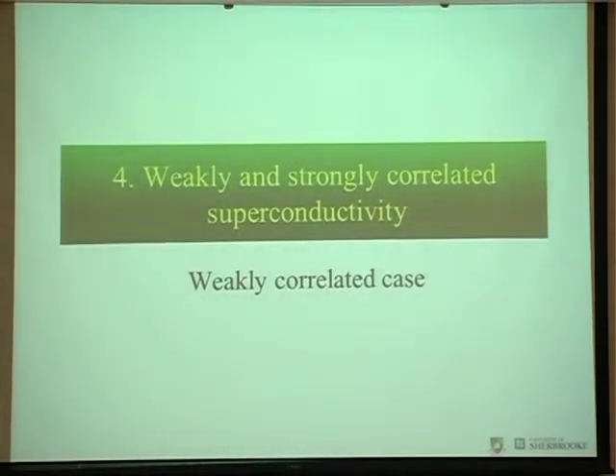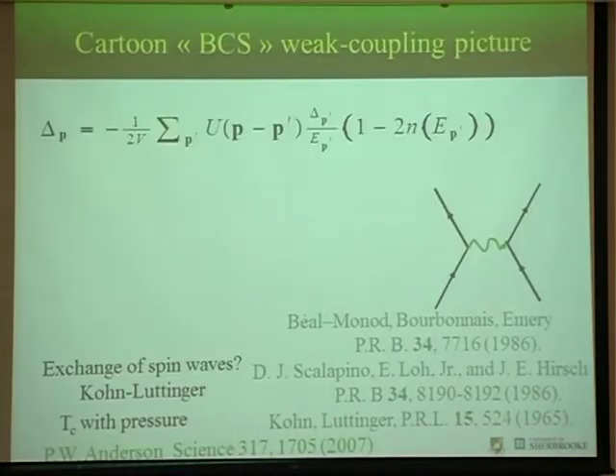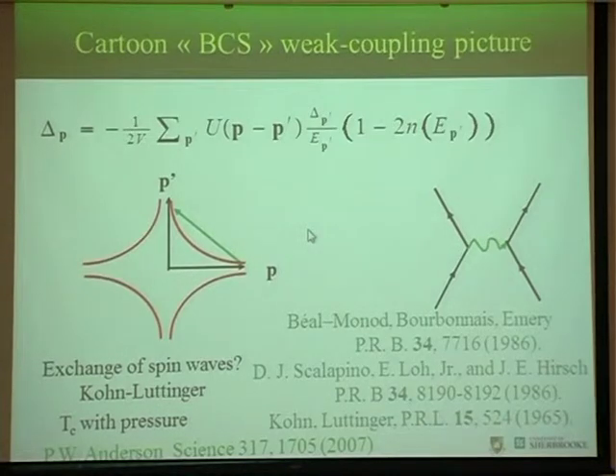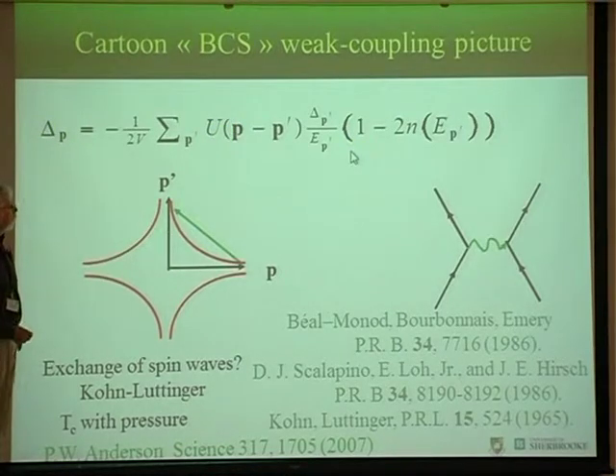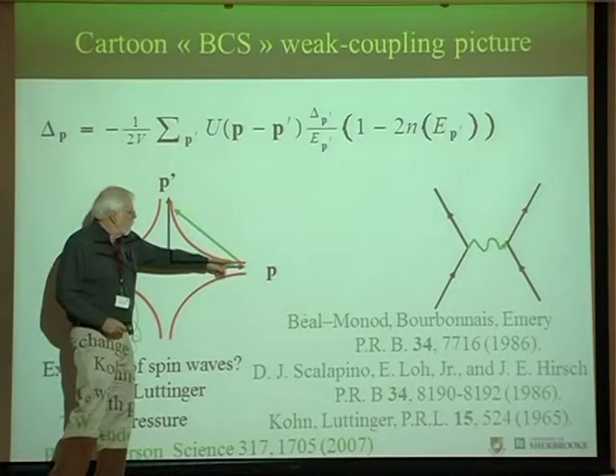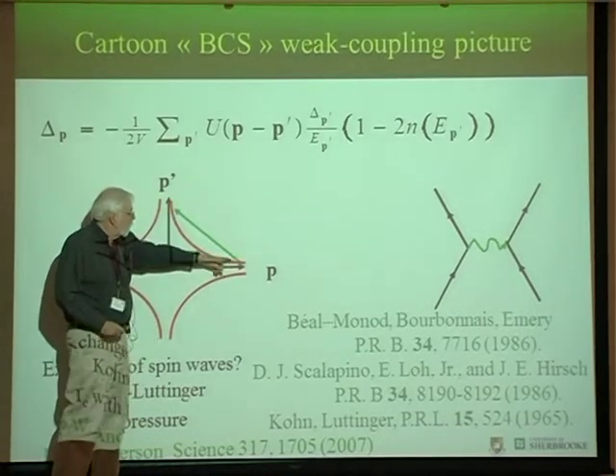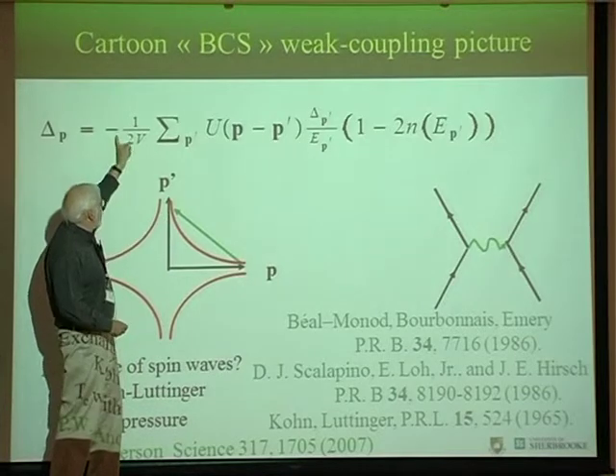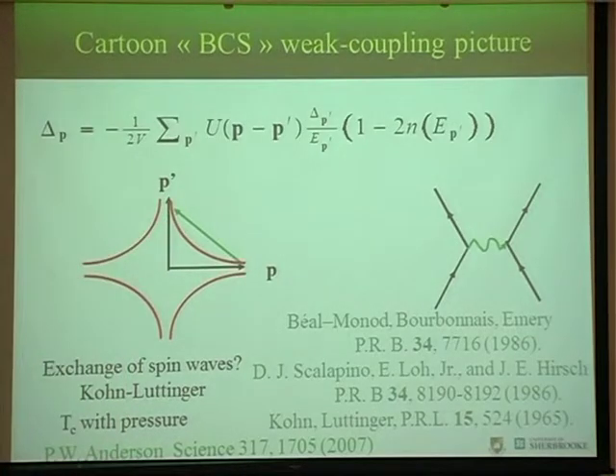So what is the mechanism for a weakly correlated superconductor? Well, this was suggested even before high Tcs were discovered, based on earlier ideas of Kohn and Luttinger, where what is exchanged here is not a phonon, like in ordinary BCS, but an antiferromagnetic spin fluctuation. Now, if this potential is repulsive, the BCS equation can nevertheless have a solution if U is large near (pi, pi), then you can compensate the minus sign by changing the sign of the gap itself.